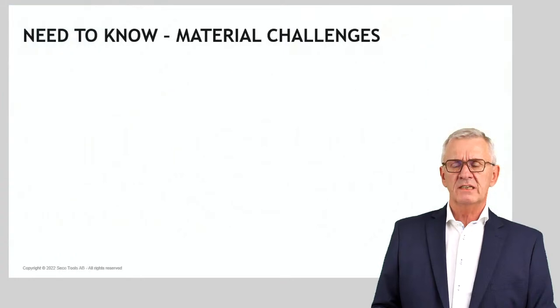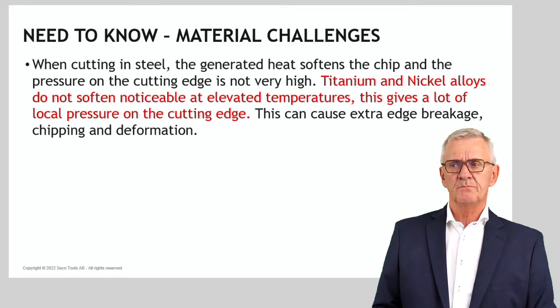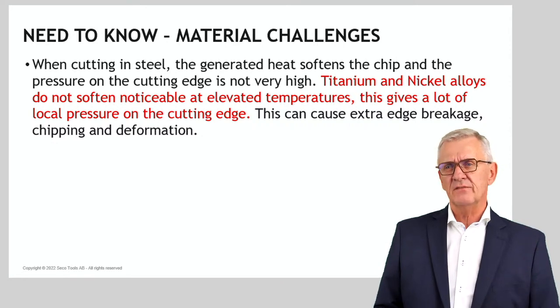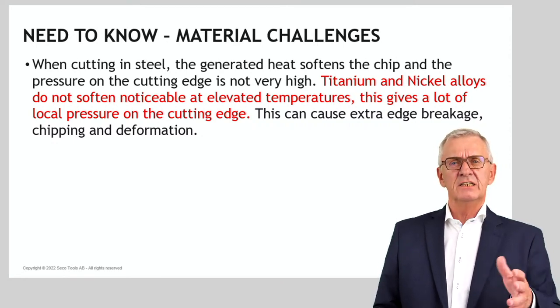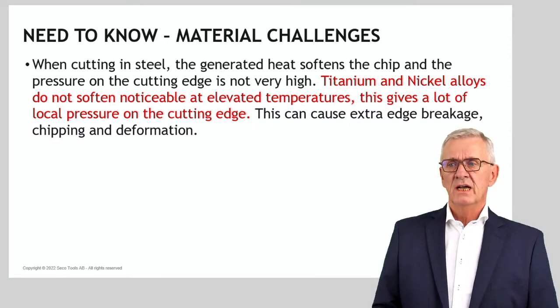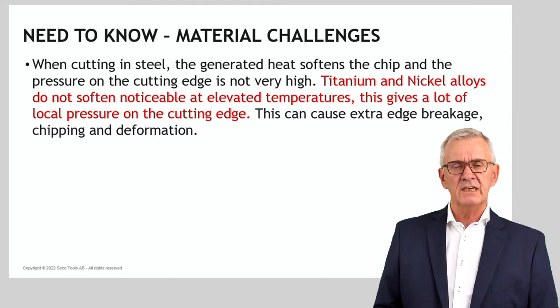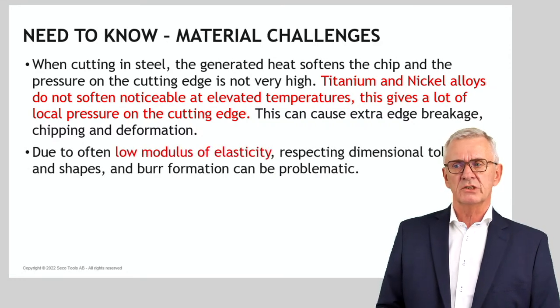If we talk about these materials, titanium and nickel-based alloys, they are quite the same thing. On the surface, they do not soften noticeably, because you have strain hardening, you have precipitation hardening, destroying a bit this system, and it will give you a very high local pressure on cutting edges. And we must be aware of, I talk a little bit more concretely, notch wear is very typical when you machine this type of materials.